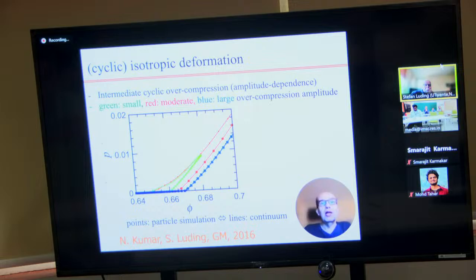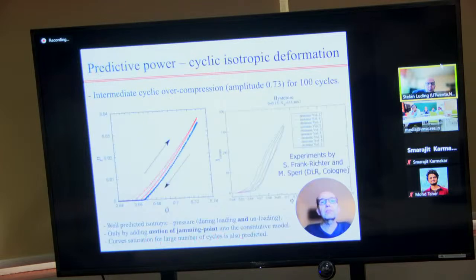Okay, the amplitude of the difference increases. The blue lines are the 100th time of loading and unloading, and actually it becomes close to reversible. It's not exactly reversible, but it's getting close. And it's different again. So the blue line is the same system as the red system, same system, same loading parameters, but after 100 times, it has a different jamming density. So it's much different. Jamming density is not a constant. It's not a point, it's a variable, and that has to be taken care of.